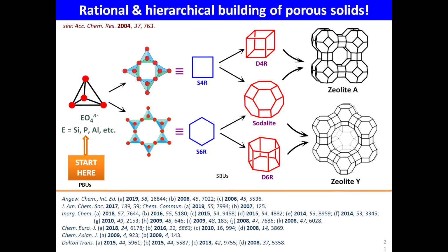So what we did was that the moment you have a EO4 n-, you can take these tetrahedra and form single rings, put single rings over single rings and form a double ring, or single rings in another fashion and form double 6 rings, or mix single and double rings together and form a sodalite, and take any of these building blocks and stick them together with a proper chemical glue and make zeolites. I think Singh is here, and this is pretty much the way they do retrosynthetic analysis, right? They take a natural product and break it into smaller rings and then make it.